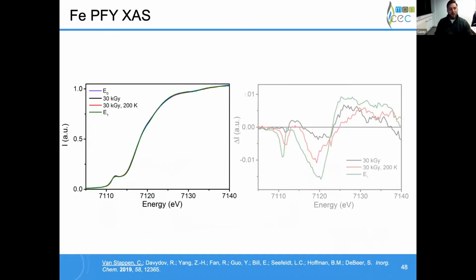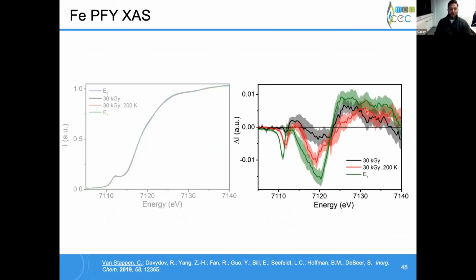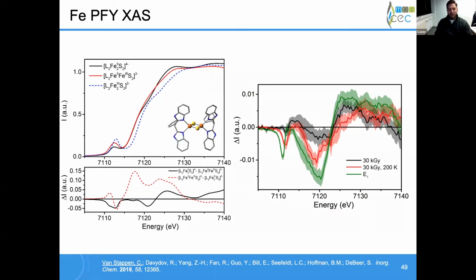So with that in mind, we can go back and repeat these experiments using partial fluorescence yield. Now we don't have as beautifully resolved spectra, but we actually have significant difference in the results. And this is really huge for this kind of very detailed experiment with a lot of unique centers present. And chemically, we see something that looks a lot like this localized mixed valent dimer. So we have a decrease in pre-edge intensity, a decrease in the rising edge, and an increase in white line intensity. The fingerprint looks a lot like this black line here.